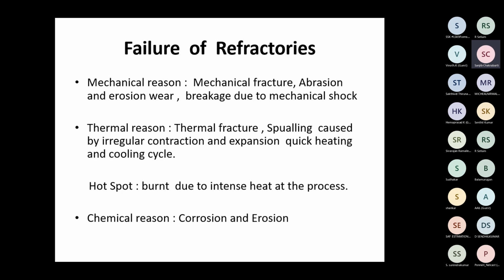A refractory brick is subjected to these, not in the steel plant so much, but in many other places, particularly heat treatment plants, where there are heating and cooling cycles. The brick has to withstand this cycle, otherwise there is spalling and breakage. Because it is a polycrystalline, polyphase material, its contraction and expansion are not of a reversible nature. It's very important: they are irreversible processes, and that causes cracks. So this has to be taken care of by selecting the right refractory.